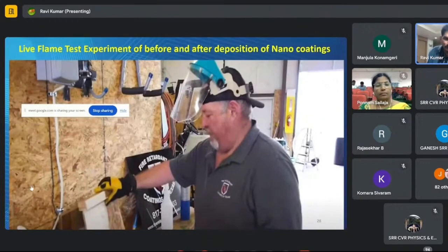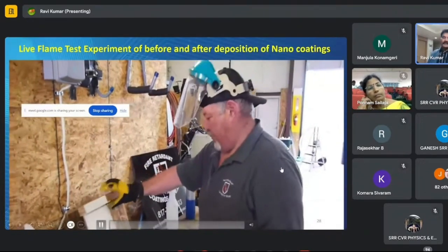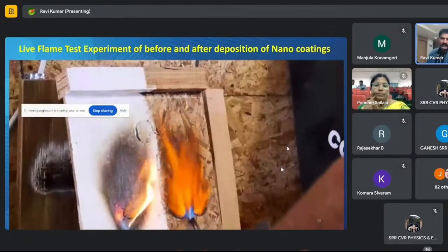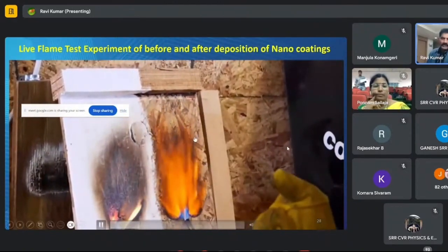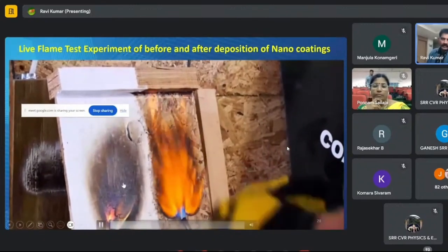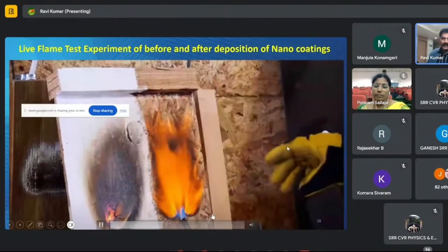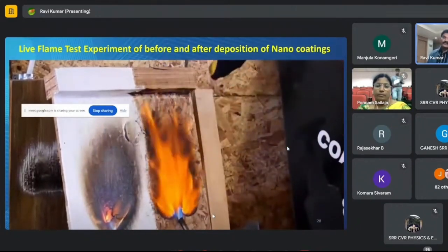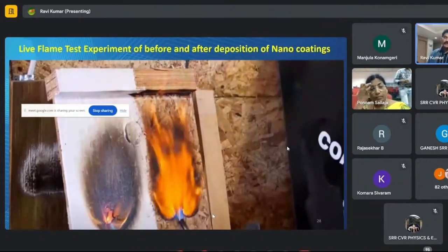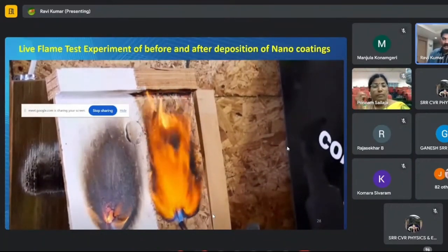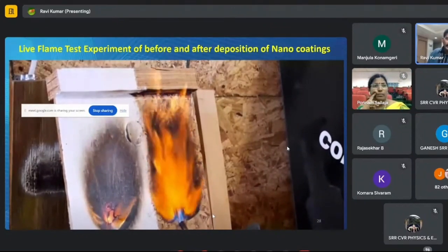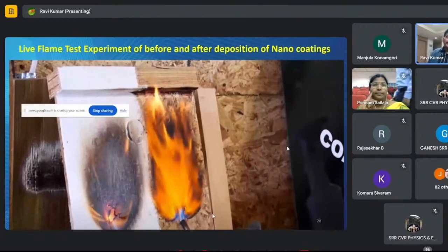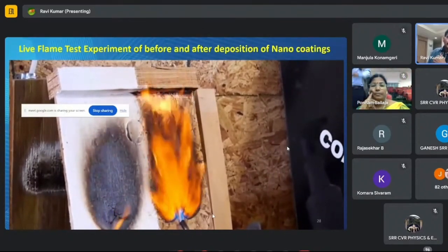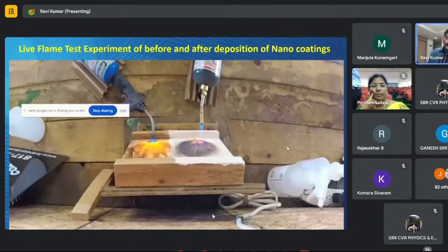Also, you can see this video before deposition and after deposition of the flame retardant material. The brown one is without deposition, the white one is after deposition of the flame retardant. So it is protecting very strongly. You can see the surface of the white and the surface of the brown. The brown is completely burning because we are giving the heat jet on the surface. It is catching fire. But in this case, on the left side, the white one with the deposited flame retardant nanomaterial doesn't allow it to catch fire. So this is the real live video to understand our research.